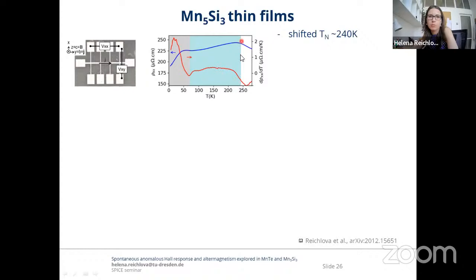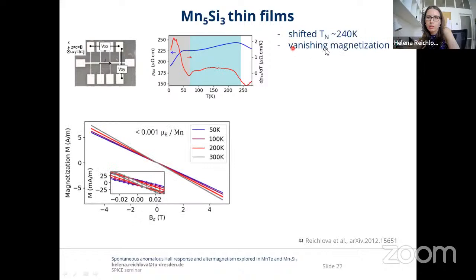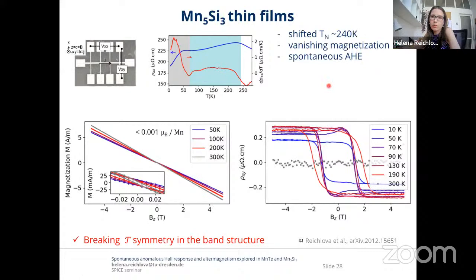These films were also studied by magnetometry, and we can see that our magnetization curves here do not show any clear measurable signal within our resolution and experimental capabilities. It's dominated by the silicon substrate and not strongly changing with temperature. And the estimate which we could give, given our experimental error, is that the moment is less than 0.001 Bohr magneton per manganese. This is in contrast to the transport measurements which we performed.